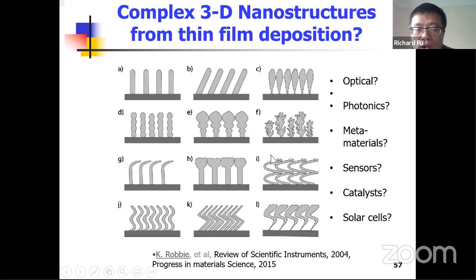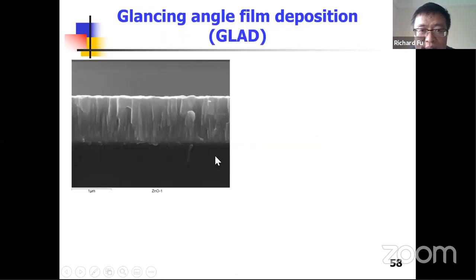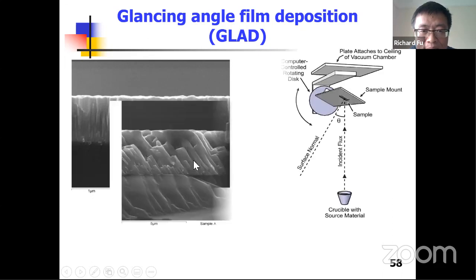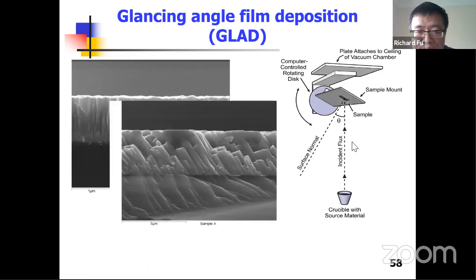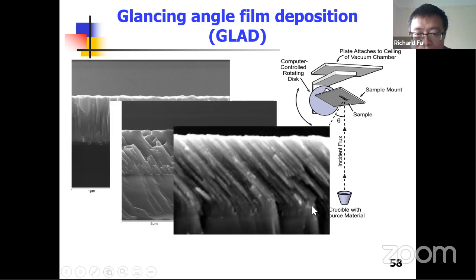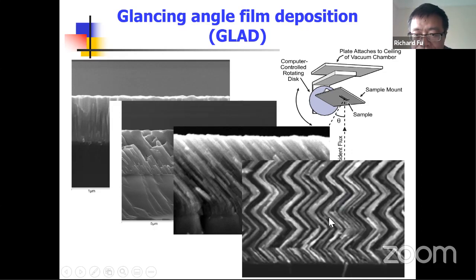So this is normally called the glancing angle deposition method. The idea behind it is that if we put the source and target vertically, then the film grows vertically in most cases. If you tilt the substrate, you can grow an inclined, angled film. If you tilt further, you gradually find there are actually spaces between them. It becomes porous. Of course, people use the tilting back and forward, and then they get a zigzag.